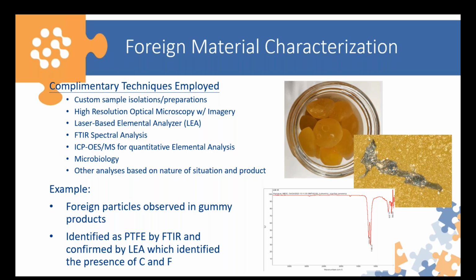So what we did is we took these gummies and we did some high magnification microscopy, and we were able to get good images of the particles. So I have an image of one of the particles here. You can see its shape and color. And then from there, we were able to isolate them and analyze them by FTIR, which identified these particles as PTFE. We were also able to confirm their identity using the laser-based elemental analyzer, which confirmed the presence of carbon and fluorine. And so using this approach, we were able to identify the particles and we were able to analyze multiples to confirm they were all coming from the same source.